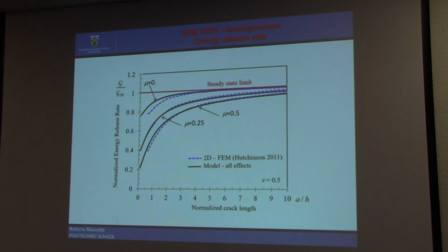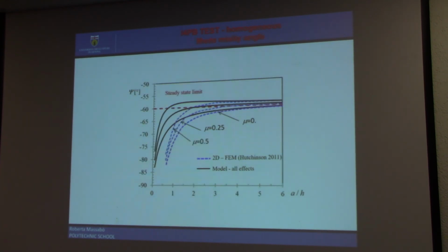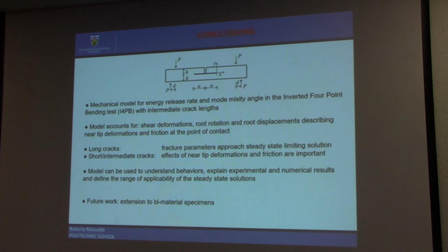You can also see by looking at this diagram that the steady-state limiting solution is approached only for very long crack length, and therefore the idea is that you can use this theoretical model in order to define the proper geometry to use in the lab if you want to propagate the crack under steady-state condition. We also obtained some results for the phase angle, but due to the lack of time and the fact that we are still not sure about those results, I will just go to my conclusions.